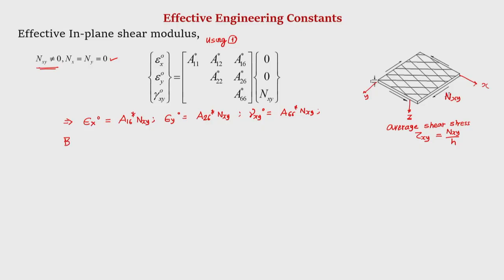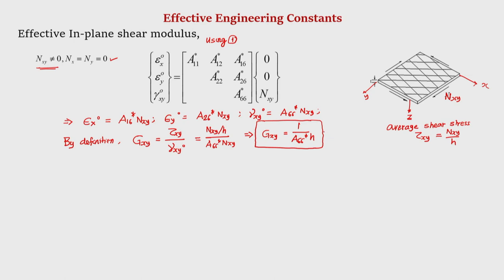Therefore, by definition of shear modulus, G_xy is the ratio of tau_xy to the corresponding shear strain gamma_xy naught. Therefore, this is equal to N_xy by h, and gamma_xy naught is equal to A66 star N_xy. Therefore, G_xy is equal to 1 by A66 star h. This is the expression for the effective in plane shear modulus of the laminate. This is equation number 8. Okay.